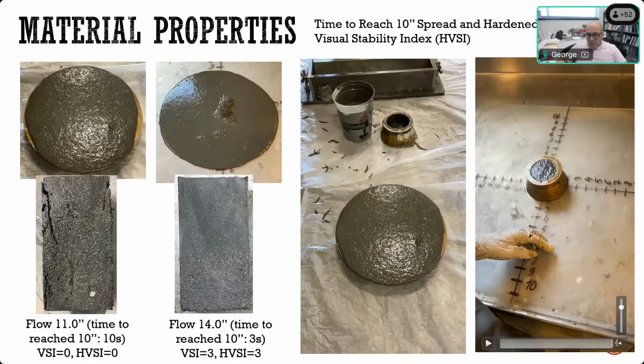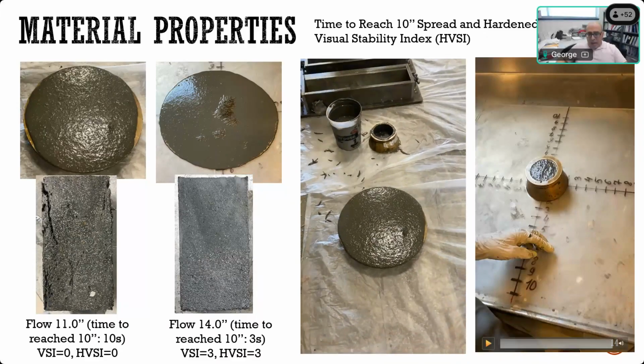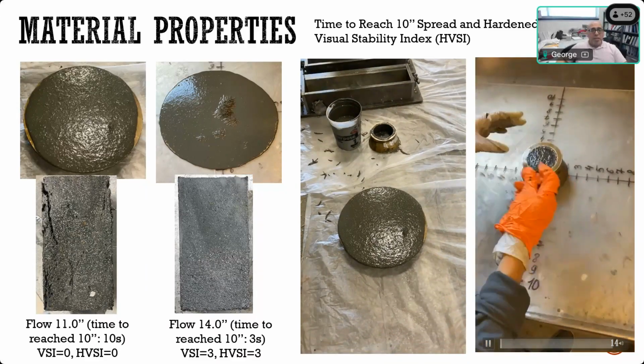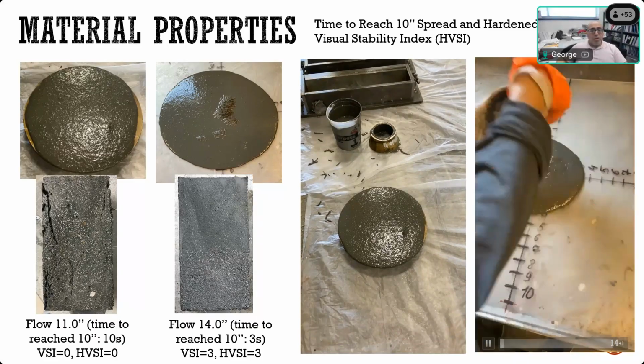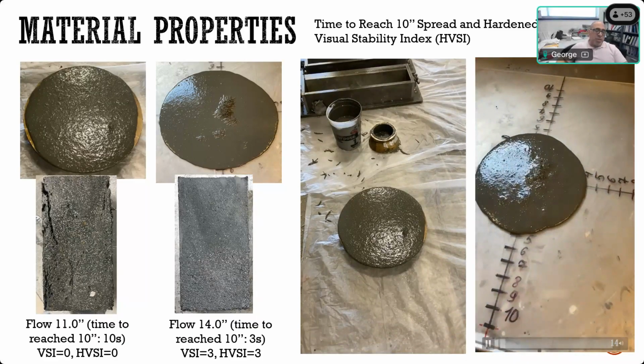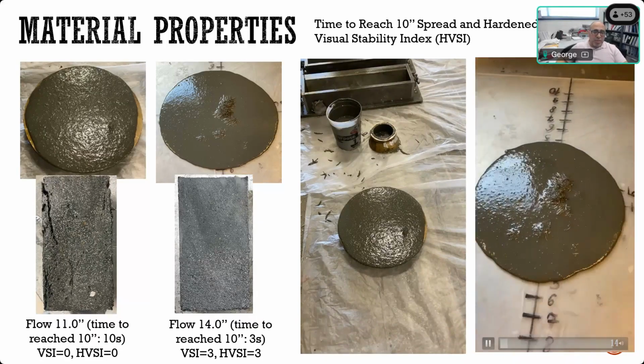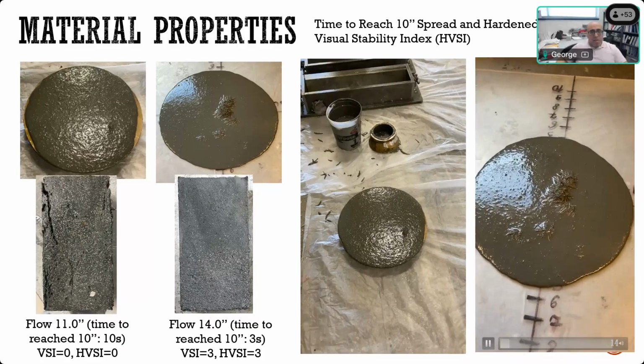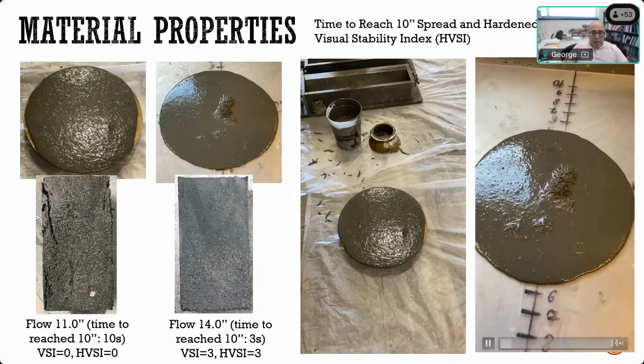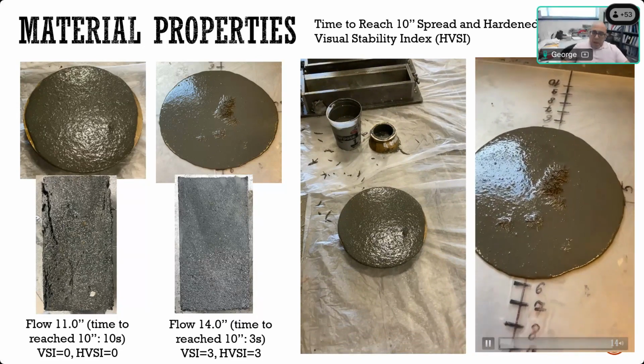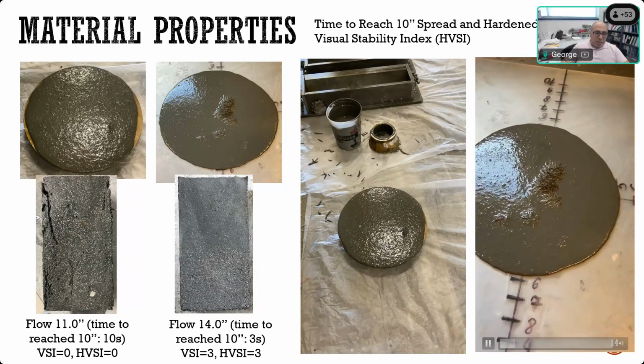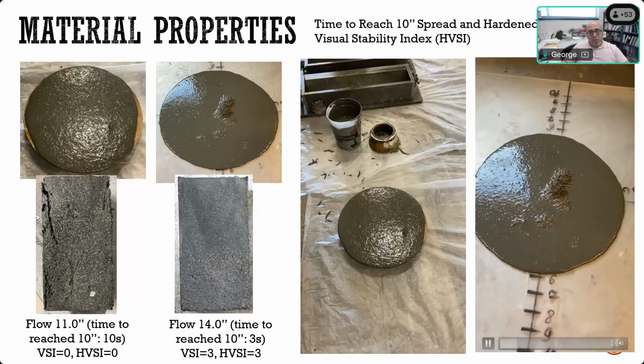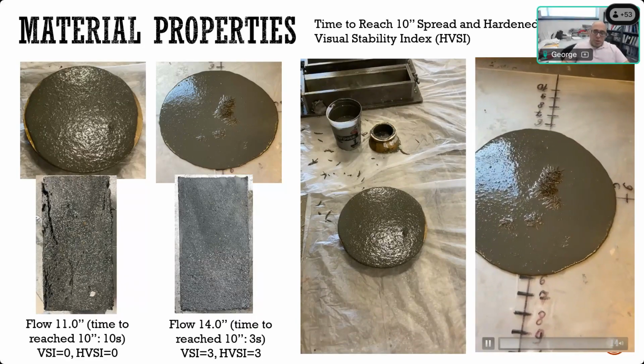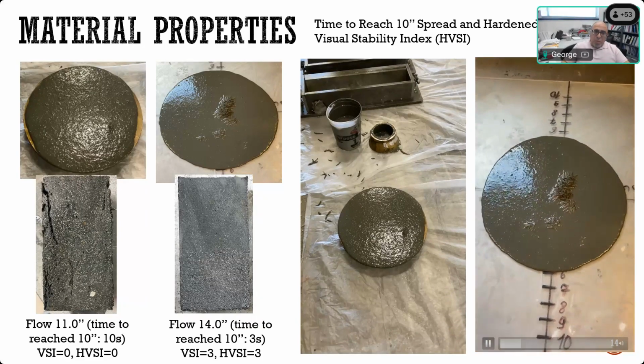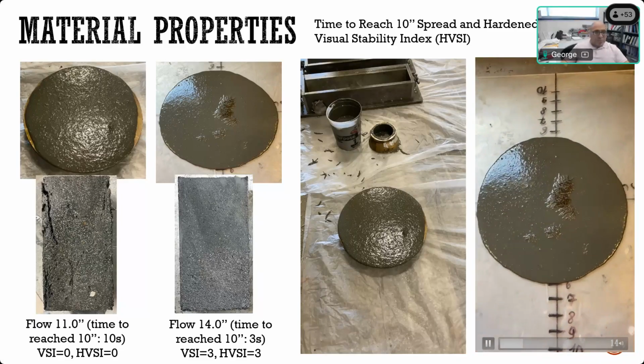But the other one here, which is not as stable, you can see what happens here. It just flows very fast. And that means it doesn't have enough viscosity, and you get some separation of the fibers. This is very important during construction. At the plant itself or the site, you do that test before you cast it in the form. Make sure it's flowable enough and stable enough.